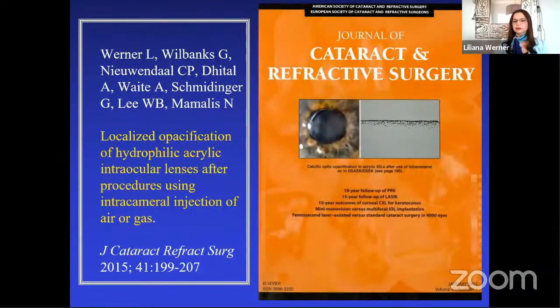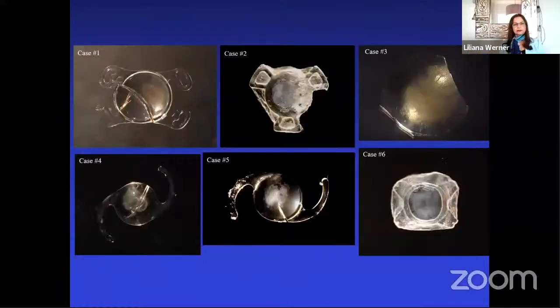More recently, we described a very specific pattern of IOL calcification of hydrophilic acrylic lenses occurring after surgical procedures using intracameral injections of air or gas, such as the DMEK or the DSEK. Different hydrophilic acrylic IOL designs were involved in this problem, and they all exhibited an overall round area of calcification on the central part of the anterior surface and subsurface of the optic. This appeared to correspond to the area of the capsulorhexis opening, where the lens material is then in direct contact with the aqueous humor.